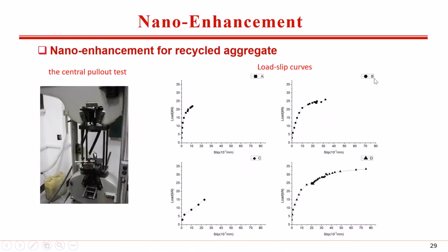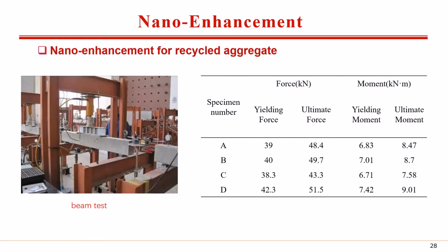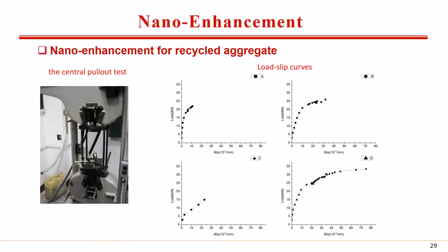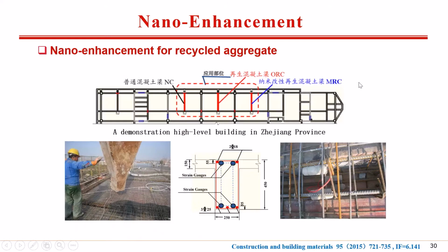Some structure properties also were conducted. We can find the force and moment of beam could be increased after nano enhancement. And the load slip curves showed obvious difference from the pull-out test. This confirms the effect of nano enhancement. In order to study the nano enhancement in real engineering, 3 beams were casted. From left, we can find the red one is the new beam. From left to right are concrete beam with 100% natural aggregate, concrete beam with 100% recycled aggregate, and a concrete beam with 100% nano-modified recycled aggregate.